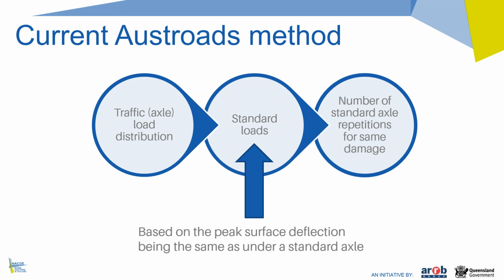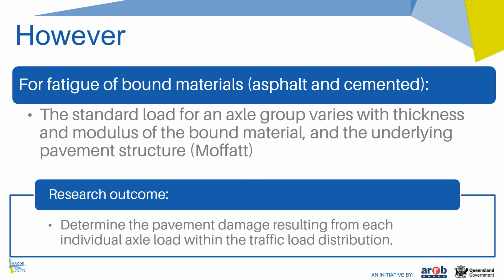However, Michael Moffat's research demonstrated that the standard load varies with pavement structure in bound pavements. The use of deflection as an indicator of damage of bound materials is therefore questionable. The research recommended that pavement damage should separately consider each axle load and group within the traffic load distribution by calculating strains under each individual axle without any conversion to standard axles. So we're proposing to introduce this new method for the assessment of asphalt fatigue damage in conjunction with the other changes that Eric and Jeffrey have covered.